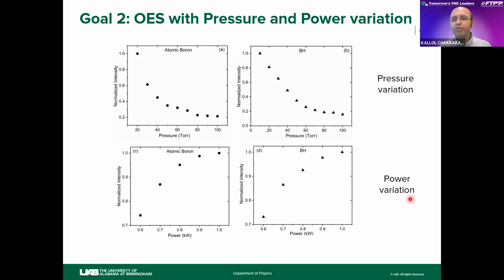Here is goal 2, where we were able to modulate or tune the atomic boron and other growth species by changing the pressure and power of the plasma. The top panel shows where we keep our power constant and change the pressure. As you can see, when power was constant and we changed the pressure, with increasing pressure, the atomic boron peak intensity decreases.